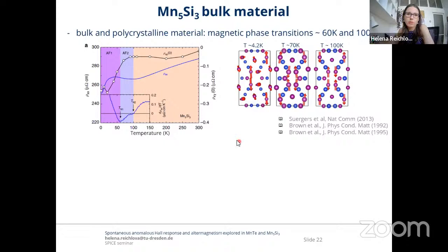And in the second part of the talk, I would like to speak about Mn5Si3, which is not so well known. It was studied in bulk and polycrystalline form. And it has actually very nice properties for us experimentalists, because it can be tuned from the paramagnetic phase into, this is what was reported in the bulk, a collinear antiferromagnetic phase and, in the low temperature, a non-collinear antiferromagnetic phase. This was studied by, for example, Christoph Sürgers or Jane Brown. And here I show the spin arrangement found by neutron diffraction.